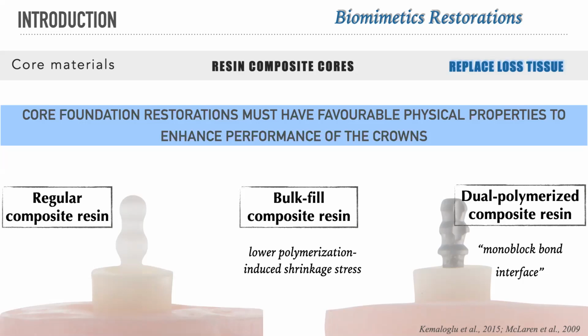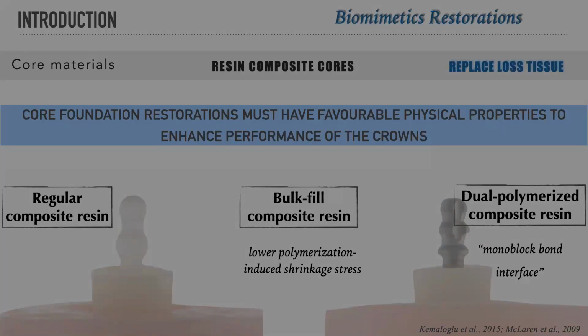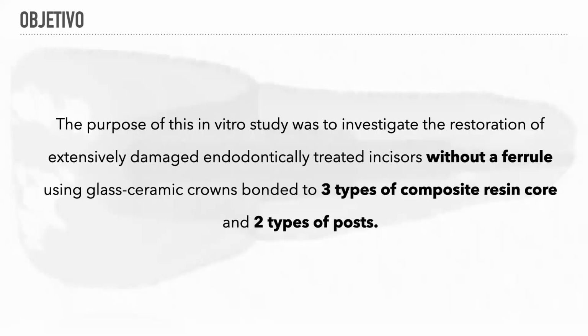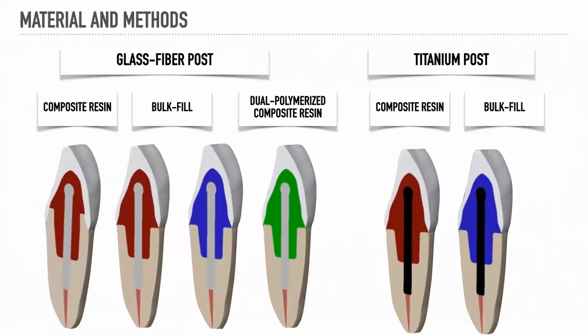So in this study, we want to find the better combination between prefabricated posts and different core buildups. So the purpose of this in vitro study was to investigate the restoration of extensively damaged endodontically treated incisors without ferrule using glass ceramic crowns bonded to 3 types of composite resin core and 2 types of posts. So here we have our 6 groups. One of the groups was with ferrule, just for comparison from the previous study, and 5 of them without ferrule. And we use 3 materials to do the buildup. One is with regular composite, another one with bulk fill composite resin, and another one with dual polymerized composite resin.